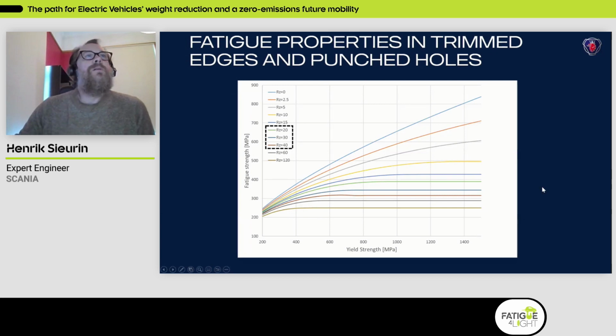And then I will move on to focus more on fatigue. As you are aware, we don't have a linear relationship between the yield strength and the fatigue strength. It depends on the surface roughness. So if you have a relatively smooth machined specimen, for example, there is almost a linear relationship. Increased yield strength gives increased fatigue strength.